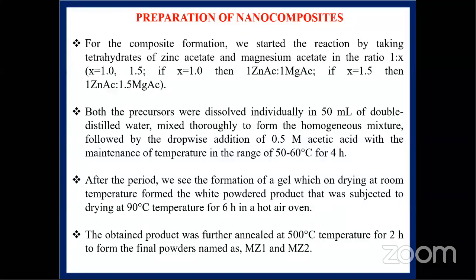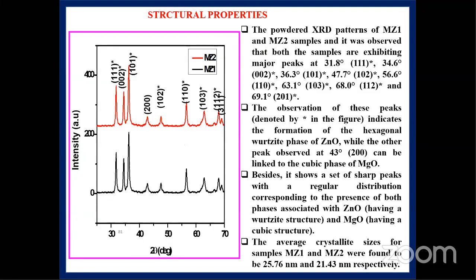After this period, we saw the formation of gel, which on drying at room temperature formed a white powder product. It was subjected to drying at 90 degrees Celsius for 6 hours in the oven. Finally, the obtained product was further annealed at 500 degrees Celsius for 2 hours. We obtained two different ratios of the sample, namely MZ1 and MZ2. You can see the XRD pattern of the MgO ZnO nanocomposite with the different ratios. The first one is MZ1 and the second one is MZ2.